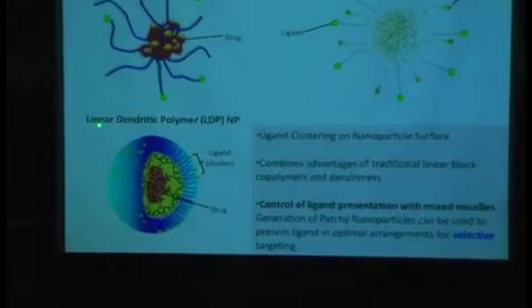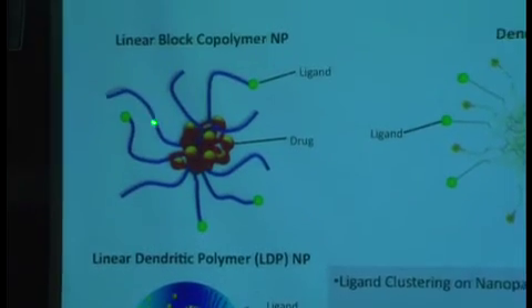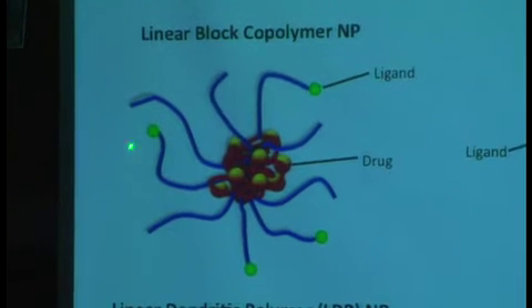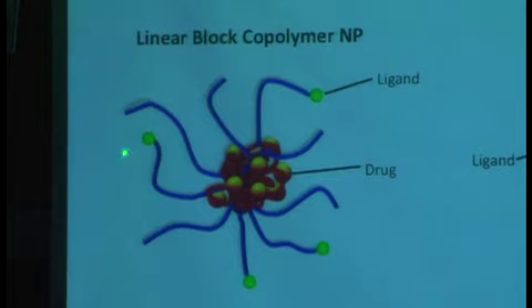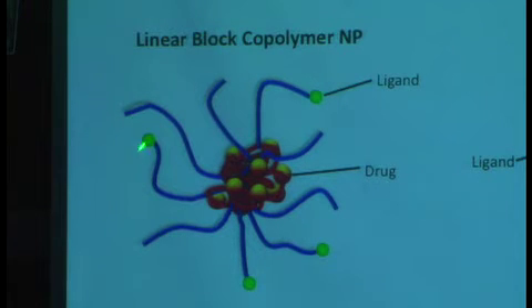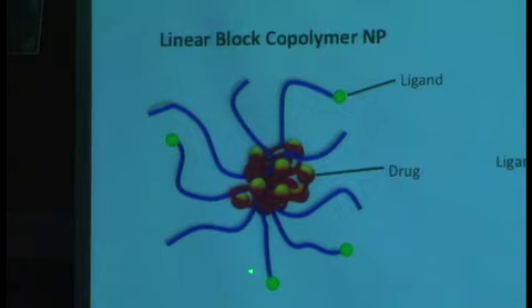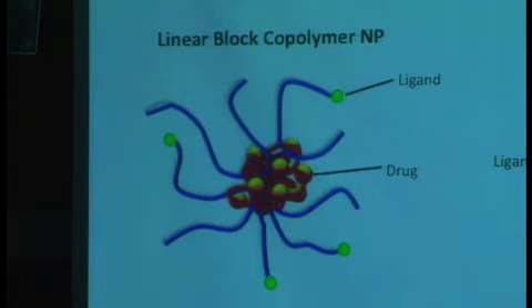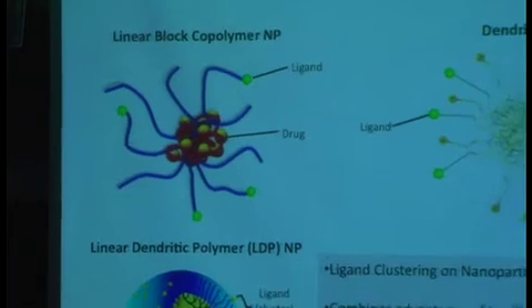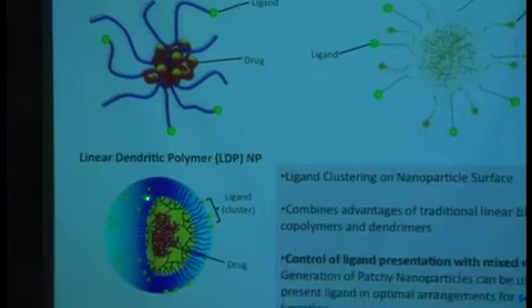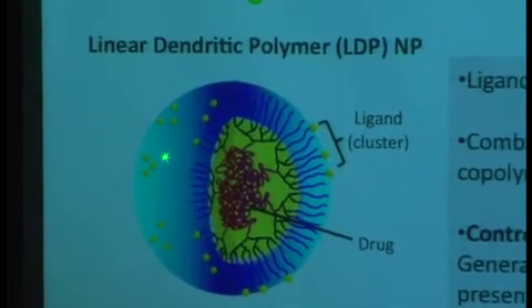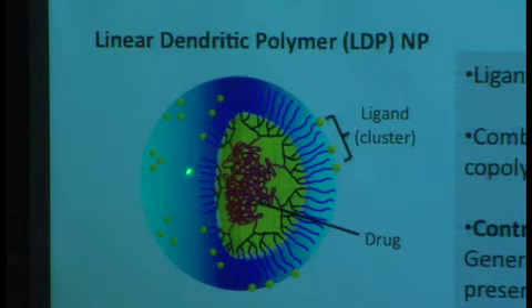For us to be able to probe this, we couldn't use our usual trick of a linear block copolymer because we actually allow this ligand to explore a large amount of space. So these are roaming around if we have a sufficient length of PEG, and therefore very difficult to contain in specific clusters. We also have an architecture which doesn't allow us to confine them effectively. So what we're actually doing is using a block copolymer architecture in which one of the blocks is linear and the other one is a systematically branched dendron, so that we can use the dendron to present the ligand in very specific predefined clusters. We then mix that with a block copolymer which does not contain ligand, and we can gain control of the spacing of these clusters and their number density on the surface.